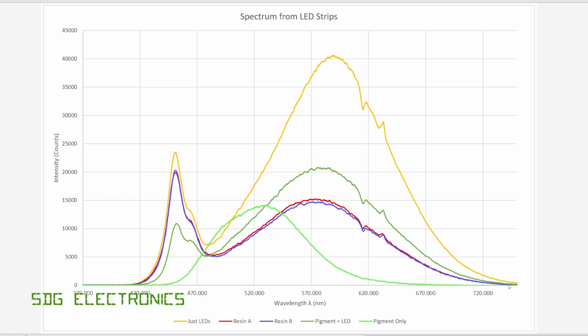Then we have our two LEDs coated in resin in orange and blue. And basically what we can see is that there is a little bit of a decrease in light output at the 450 nanometer region, but there is a significant difference in the orangey red region up here near 600 nanometers. So although some decrease in general light output is to be expected based on the thickness of the resin, it would appear that the resin itself has a huge amount of absorbance in this 600 nanometer region, which is why we see that very big shift in color temperature, because basically it's stealing a lot of the light in that orangey red region.